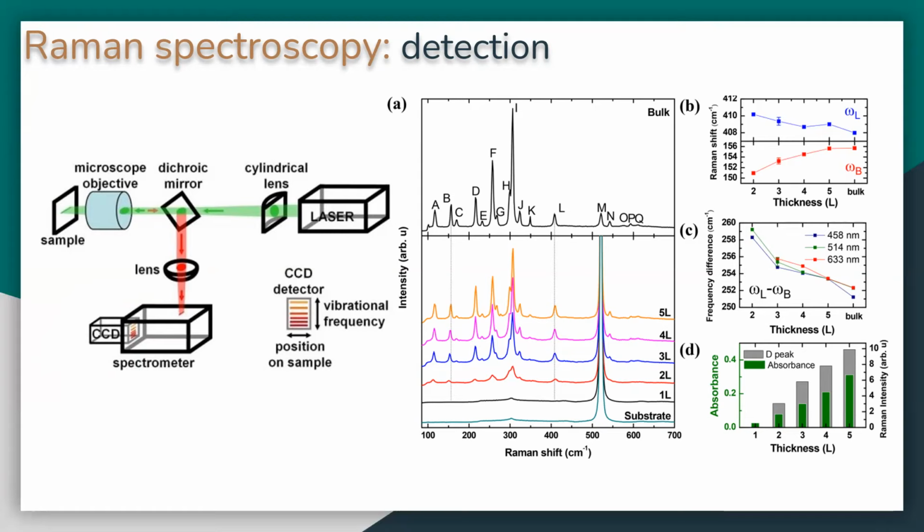The line widths become smaller as it approaches the bulk amount. There is a decrease in the line widths in the 2 and 3 layer, and this is due to substrate interaction because the material gets so thin. And hardening also occurs with increasing thickness in van der Waals interlayer interactions, even though the layers are weakly coupled.